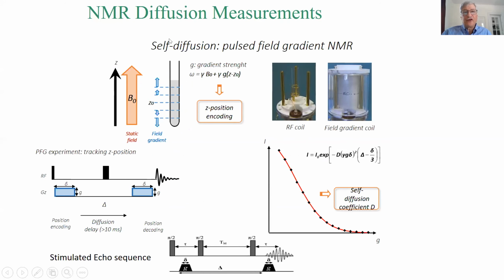We use a fairly standard technique called pulse field gradient diffusion. So I won't bore you with the details, especially since I don't have much time. But using these various radio frequency pulses and non-uniform magnetic fields, we can get a signal that decays as a function of time. And the only fitting parameter to fit this decay is the so-called self-diffusion coefficient of the ion that we're looking at, the nucleus. And this is very closely related to how well the ions move inside of a material.